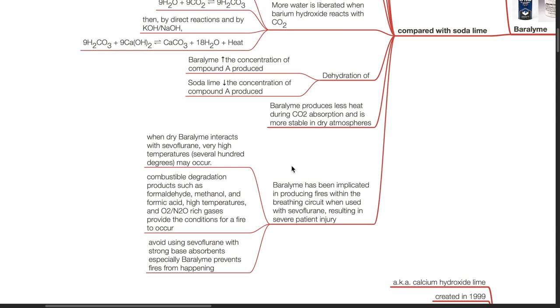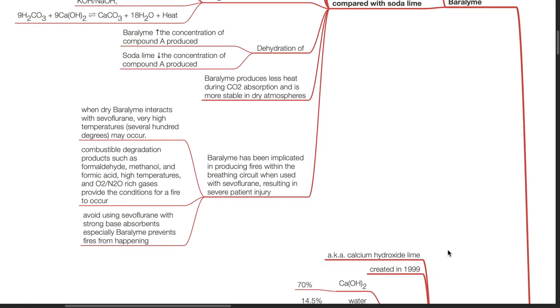However, baralime has been implicated in producing fires within the breathing circuit when used with sevoflurane, resulting in severe patient injury. When dry baralime interacts with sevoflurane, very high temperatures up to several hundred degrees may occur. Combustible degradation products such as formaldehyde, methanol, and formic acid, combined with high temperatures and oxygen- and nitrous oxide-rich gases, provide the conditions for a fire to occur. Avoid using sevoflurane with strong base absorbents, especially baralime, to prevent fires.